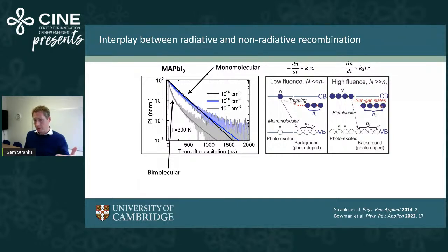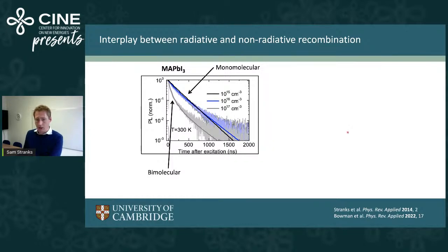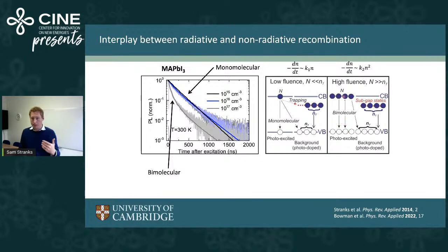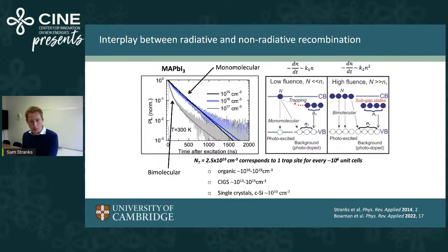If we fill these traps, if we have higher excitation densities, it means we have comparable numbers of electrons and holes. And so this becomes second order. We see bimolecular recombination. And that's what we would expect for a semiconductor when we're generating electrons and holes. It should be second order. But one of the things we can extract from this model, and this is one of the most important parameters, is we can extract the trap density.